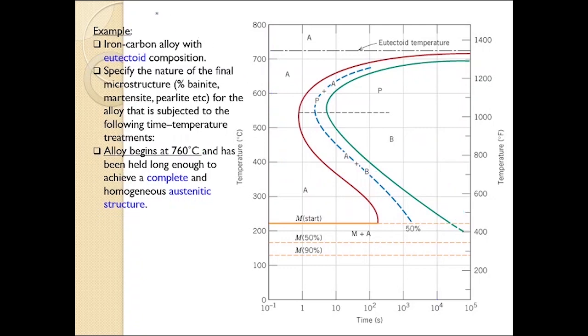So we already learned about pearlite and bainite. What if we want to get the final product of 50% pearlite, 50% bainite? So as usual, we start at high temperature above the eutectoid temperature. We supercool the austenite until around 650 over here. When we supercool, the austenite is maintained at 100%. And then we maintain at 650 degrees Celsius until the center line or this dashed line.